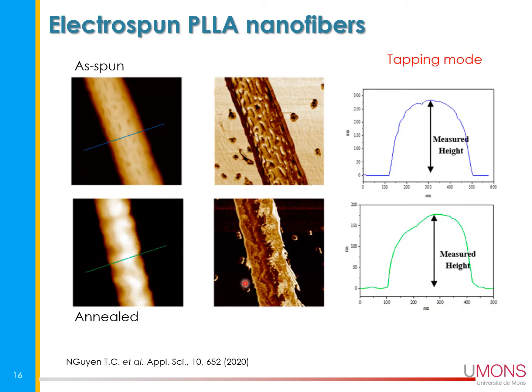So this is what we observe in tapping mode, which is just the mode, as I told you before, to measure the topography of the sample. So this is the as-spun nanofiber, just one isolated nanofiber. This is the topography, this is the phase, and you can see that you can distinguish the fiber, which appears softer than the substrate, which was here a glass substrate, and we can measure the diameter of this fiber being about 250 nanometers.